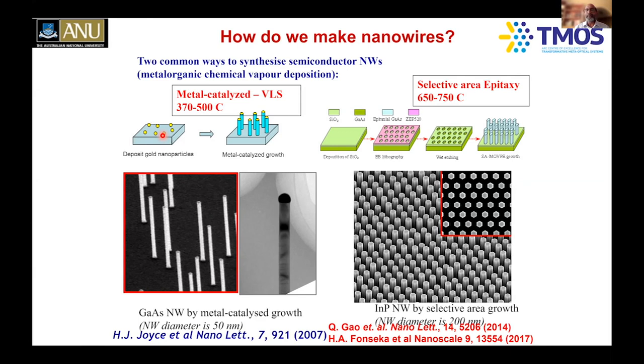So now we put these gold nanoparticles on top of gallium arsenide, for example, put this into the MOCVD reactor, heat it somewhere between 370 to 500 degrees Celsius, and then you are creating the gold gallium eutectic liquid alloy. Then you introduce the gases needed for the growth of gallium arsenide, trimethyl gallium and arsine, and they end up incorporating into this liquid alloy. It gets supersaturated, and crystals start splitting out. This is like dissolving sugar in water: up to the solubility limit, sugar dissolves, and above that, it starts crystallizing or precipitating out. That's exactly what is happening in this case.